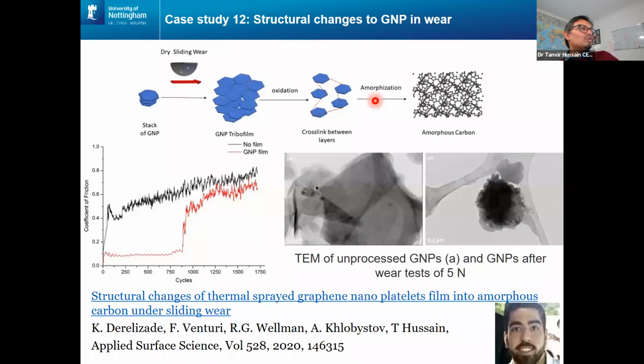Moving on to a bit more structured work. Here we were looking into what happens at an atomic level during dry sliding wear of these graphene nanoplatelet stacks. It tends to form a tribofilm, which goes through oxidation and forms cross-linking between the layers, eventually ending up with amorphization, turning into amorphous carbon. The coating does work up to a certain number of cycles, then the film breaks down, and you can see the coefficient of friction going up.